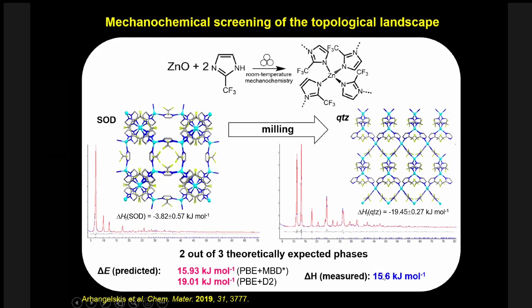So again, by controlling the reaction conditions, and this was done deliberately, this was not an accident, because we looked at the reaction, we realized there was an intermediate form that we need to somehow stop the reaction at that level. And then the person who did the work, our postdoc Thanasis, said, well, I'm going to grind softer. I'm going to use materials which have lesser Young's moduli than, for example, steel. So he switched to Teflon milling jars, which are softer and gentler, and milled at a lower frequency, went down maybe to 25 hertz, and then added the liquid that can occupy the pores. So with all these measures applied, you can actually isolate these less stable open framework materials.